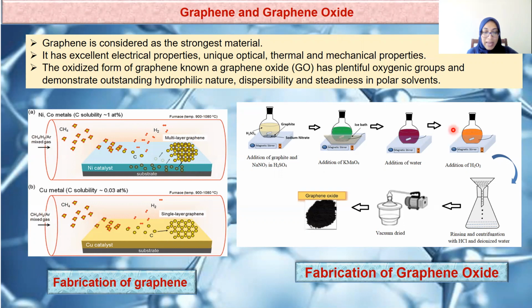The mixture is diluted by adding water, and stirring continued. Later, the solution was left without stirring for the particles to be collected at the bottom, and the excess water is filtered out. The obtained mixture is cleaned thoroughly by centrifugation with hydrogen chloride and deionized water. The gel-like product obtained is then vacuum dried to obtain graphene oxide powder.